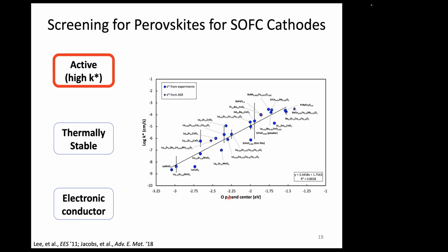It basically relates to the energetics of oxygen. So it makes some sense that the energetics of oxygen relates to the surface exchange coefficient of the same atom, oxygen. And you can dig into that in more detail, but the correlation looks reasonably good. So we can use this now to take any material, calculate the p-band center, and essentially read off from this line what surface exchange coefficient we think we're going to have. So that's our first pillar that we're going to build on.